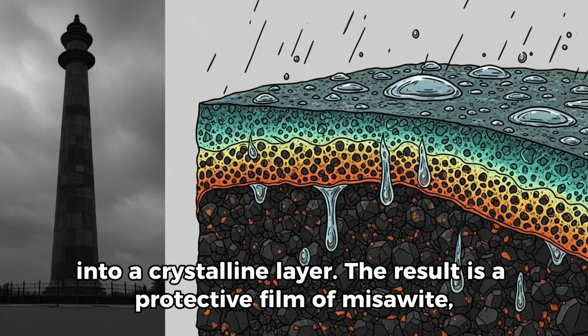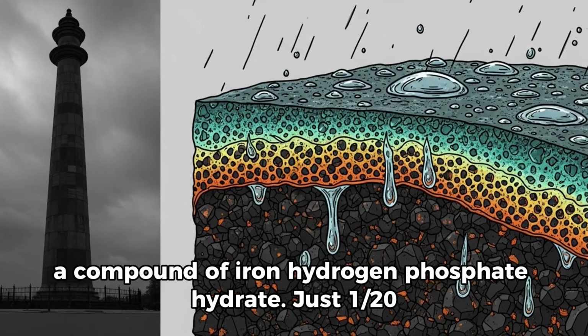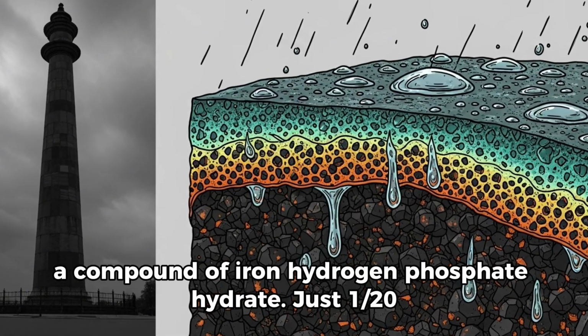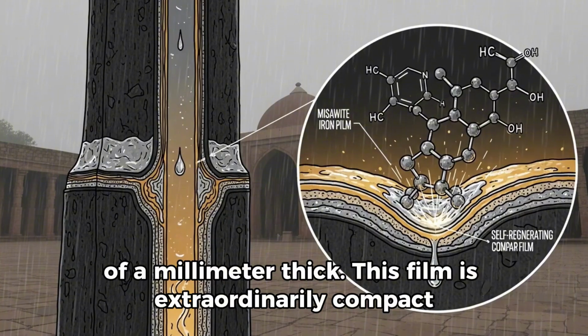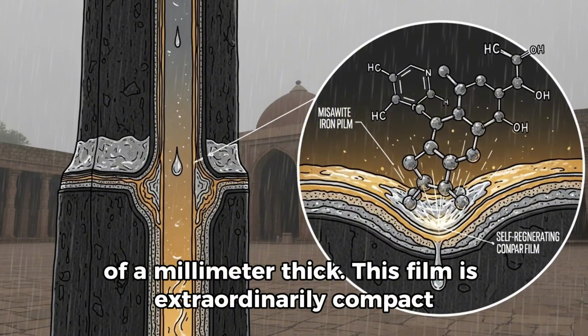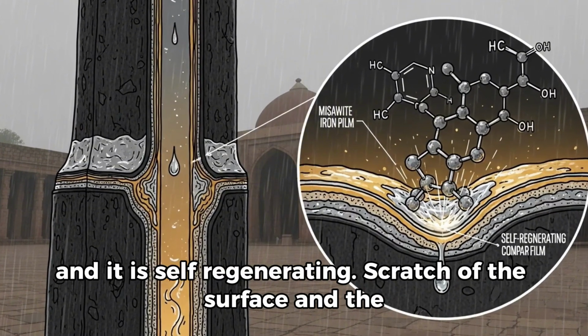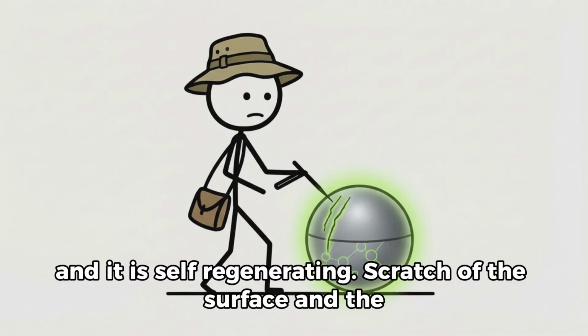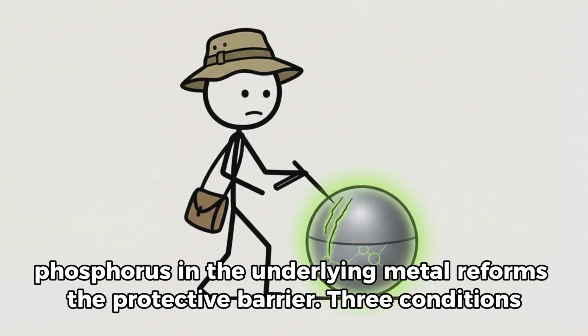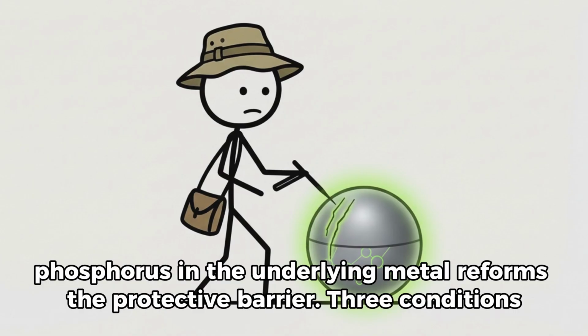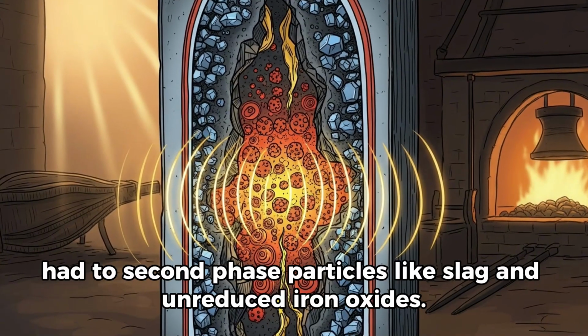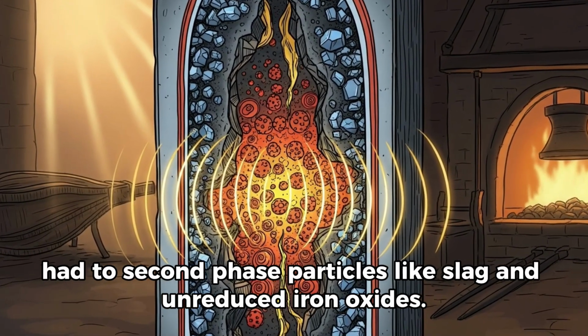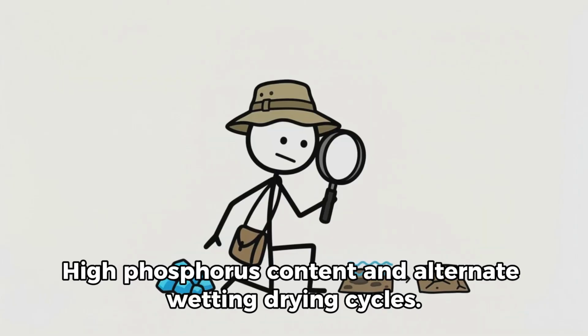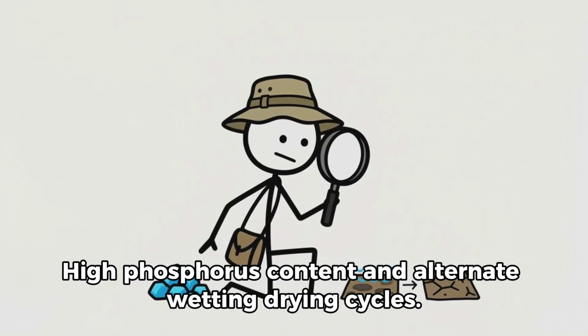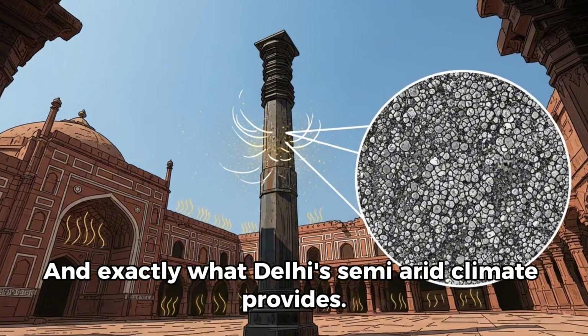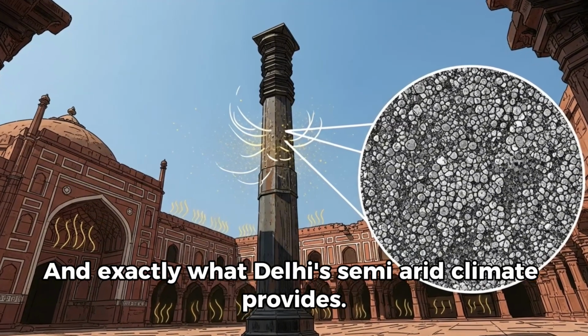The result is a protective film of misawite, a compound of iron hydrogen phosphate hydrate, just 1/20th of a millimeter thick. This film is extraordinarily compact, and it is self-regenerating. Scratch the surface and the phosphorus in the underlying metal reforms the protective barrier. 3 conditions had to align: second phase particles like slag and unreduced iron oxides, high phosphorus content, and alternate wetting-drying cycles, exactly what Delhi's semi-arid climate provides.